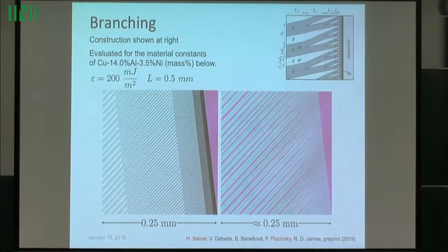You can get a very nice agreement between the branching construction and the actual microstructure with the right number of generations and so forth as you approach the austenite-martensite interface. The effect of this branching is quite, in some sense, dramatic. In the naive construction that I did, all the energy is in this transition layer, and there's no elastic energy back here. In this model, with branching, the elastic energy is quite diffuse, so it delocalizes the elastic energy away from the interface, and it adds interfacial energy. So in some sense, this provides a potential reason for hysteresis. Okay, so that's the one I want to explore.